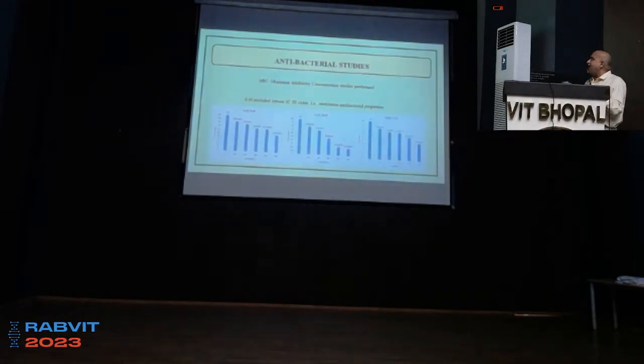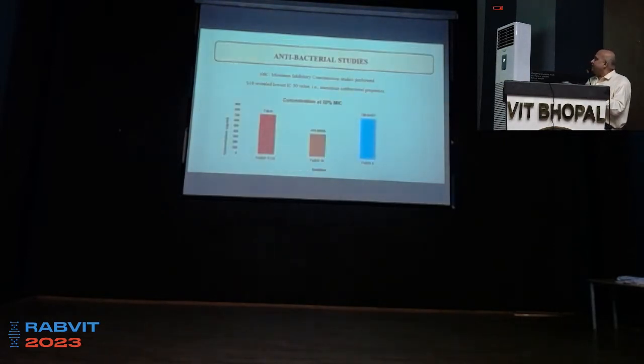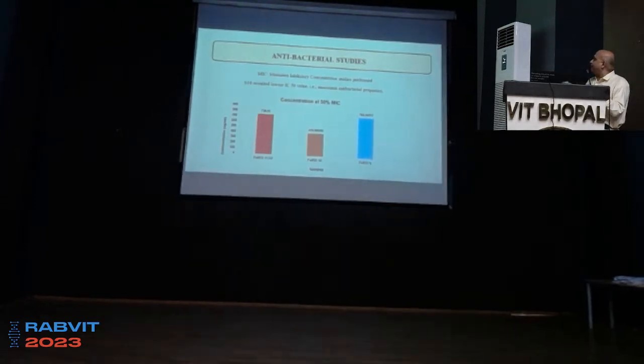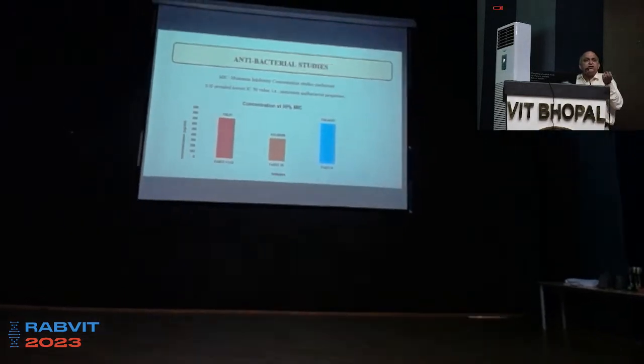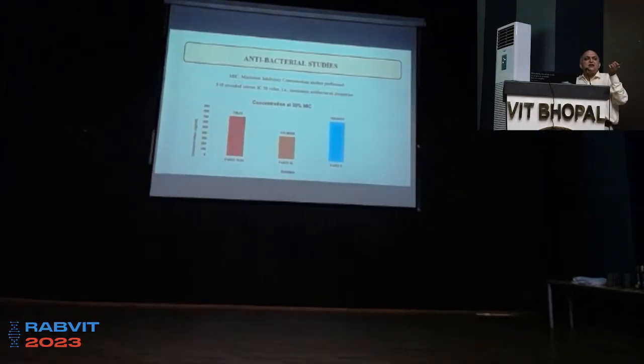So this is one of the observations which made us rethink about how the structure is evolving with the change of the pH. This was mind-blowing, and then we also looked into the antibacterial studies at this point, and we found that the MIC, the minimum inhibitory concentration, that is the minimum concentration needed to attain a 50% killing of the bacteria, is also minimum for this one. So we need the positive charge for this E. coli bacteria. So by reducing the charge of this and the zeta potential, we have achieved this point. So you see how directly it is correlated to the structure and how you make your sample.